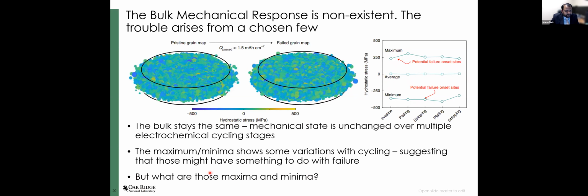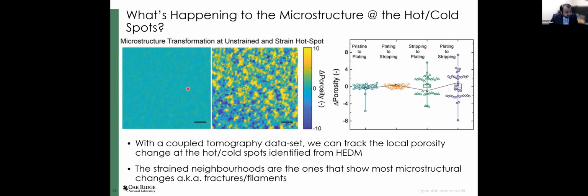So we wanted to probe what those maxima and minima are. When we did these diffraction microscopy experiments, we also did a simultaneous tomography measurement. So we were able to track not only the grains, but also the physical microstructural properties like pores and porosity at those physical regions inside these pellets. If you track the porosity changes between the pristine and the failed sample in a region where we did not see a stress hotspot, where there was no chemomechanical response of the grain, the porosity change is essentially 0. We see no difference in the microstructure before and after failure.